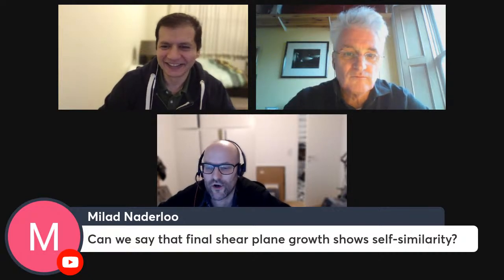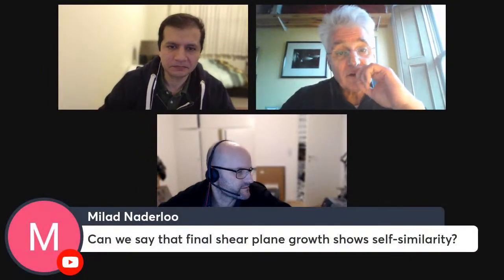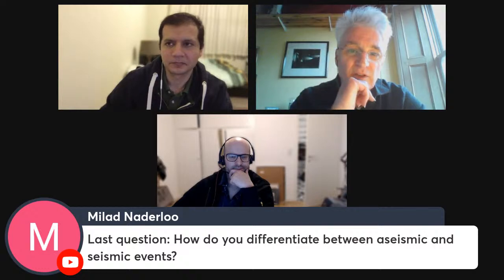So can we say that the final shear plane growth shows self-similarity, which is a follow-up question by Milad? It probably does if you define the strain as the amount of shear divided by the length of the zone with relatively high shear. That probably is self-similar growth, though we haven't checked that. In terms of the width of the deformation band, no. The width stays pretty constant. It doesn't grow that much, in these tests anyway.